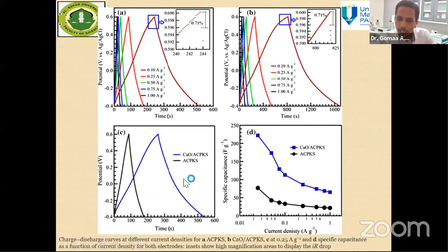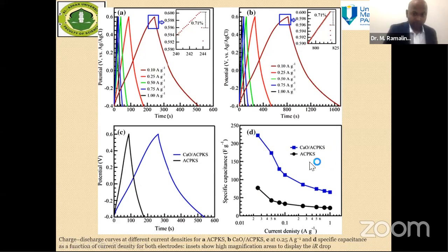So here the charge curve is wider, or a long time curve, showing the higher charge accumulated, and the specific capacitance calculation shows the specific capacitance for the nanocomposites is more than 2 times or maybe 3 times higher than pure activated carbon from the same source.